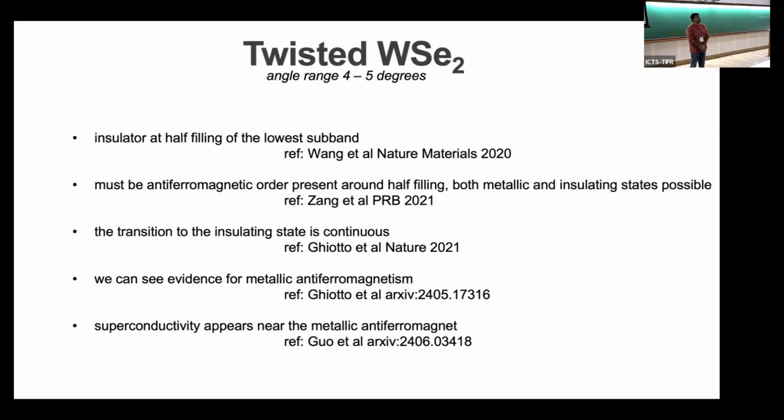Okay, so there's a question back there. Arun, there's one back there. Yeah, I have a question related to the first question. You see there is a change in the slope of the Hall data, and you say it's because of multiband. But does that really tell that antiferromagnetism is there from Hall data? No, all it tells you is that if you take the data literally, that it's multiband, there is a Fermi surface reconstruction. If you ask what the real evidence is that it's a spin density wave versus a charge density wave, for example, it would just be the sign of the interaction, which we have no reason to believe is attractive. And so that's really a theoretical statement. But any Fermi surface reconstruction would reconstruct the Hall effect. Okay, thank you.